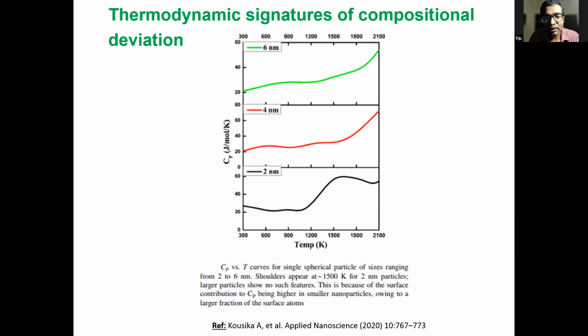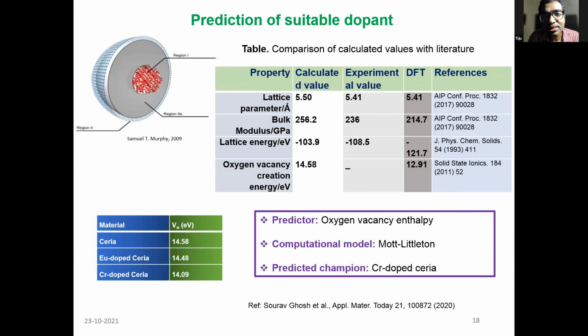Next slide, please. So in that context, we developed an adapted version of something called the Mott-Littleton method. So the adaptation was as follows. If you want to capture the thermochemical detail, in particular the enthalpy of vacancy formation, let's say, in these kind of systems, you can divide a particular defect and its neighborhood into two parts. And there is some detail to how you divide it and so on. But if you do that cleverly enough and look for the right numbers, it turns out that you can actually get the enthalpy in a very, very computationally efficient manner.